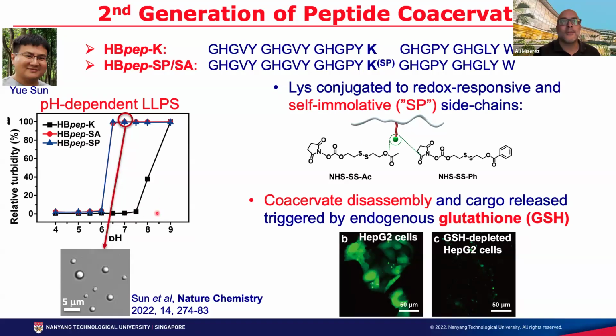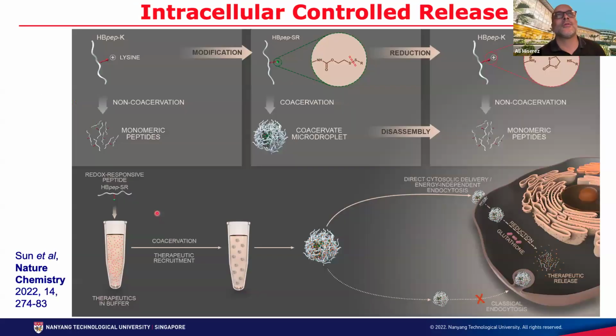If you didn't follow, there is a cartoon which should be easier to understand here. So basically you have this initial peptide with an extra charge that we add, it's a lysine. Under those conditions, you don't have phase separation. Then this peptide is chemically modified. So you actually block this charge, and you're able to form those coacervates.